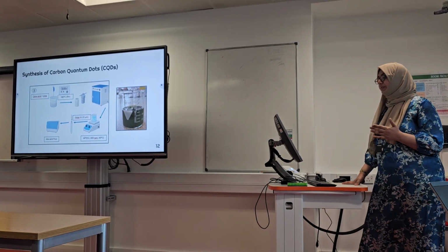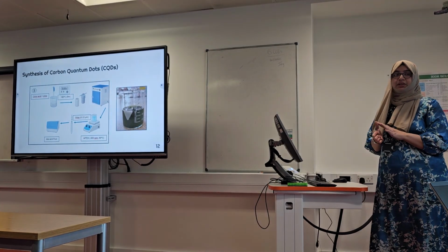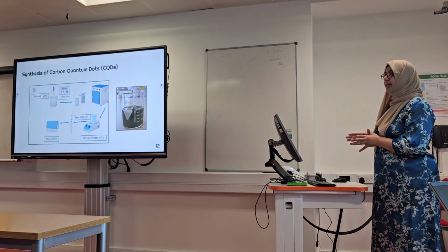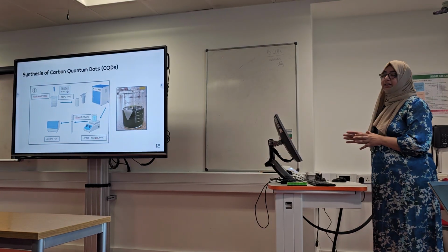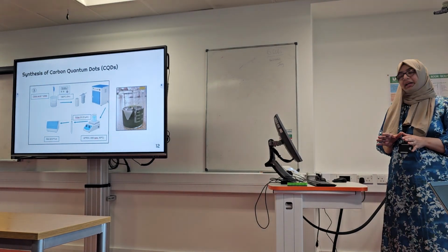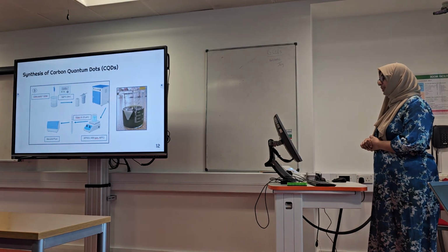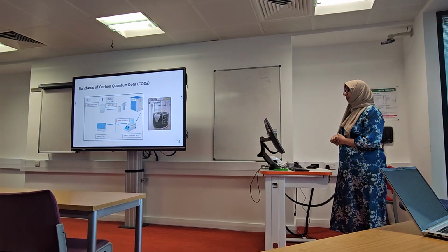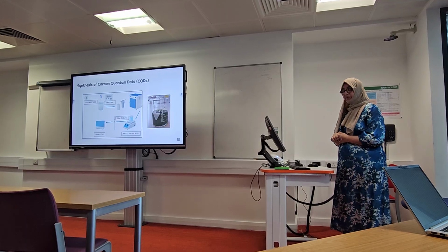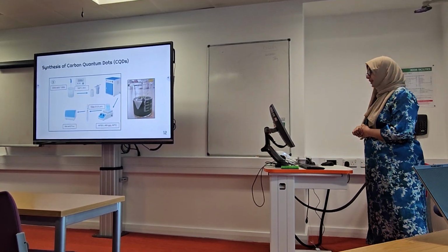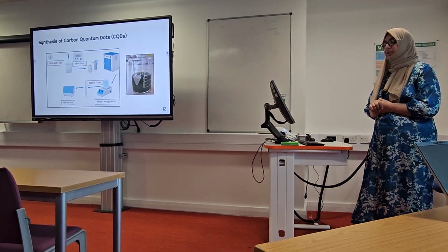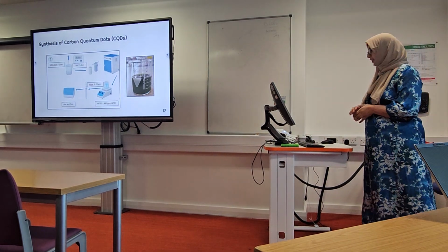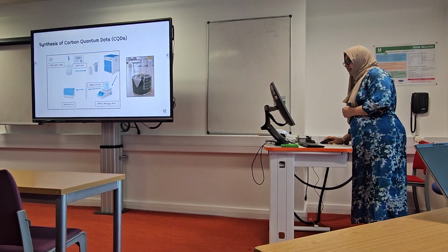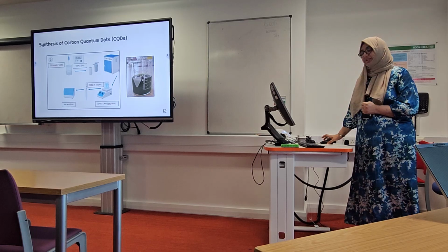But here, first I used citric acid and urea, and after the hydrothermal reactor, I added around 4 ml of APTES for surface functionalization, and then put it on stirring for 2 hours, around 400 RPM at 60 degrees centigrade, then filtered the solution and checked the absorbance and fluorescence. Here is the end product. The color is dark green.